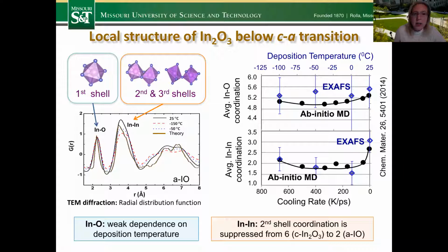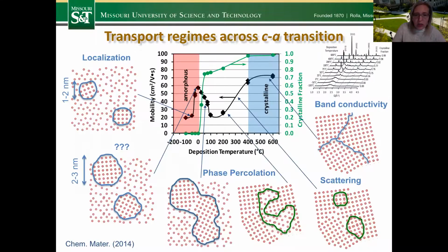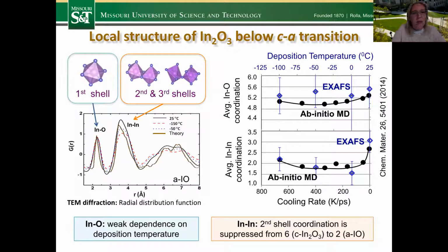However, there are significant changes for the second and third shells, which correspond to the sharing between the corner and edge-shared polyhedra. So the indium-indium, metal-metal distribution is affected. Now, how can we align the theoretical cooling rates? We are using molecular dynamics and different cooling rates with the deposition temperature.